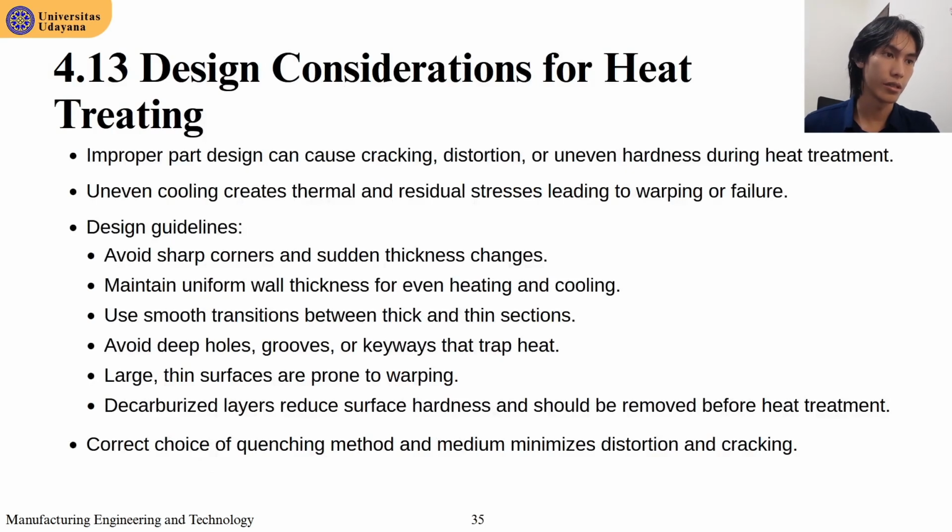Okay, and the last one is design consideration for heat treating. Design parts to avoid cracking and distortion: avoid sharp corners, keep uniform thickness, use smooth transitions, and limit deep grooves or asymmetry. Choose the proper quench method and remove decarburized layers before treatment to improve results.